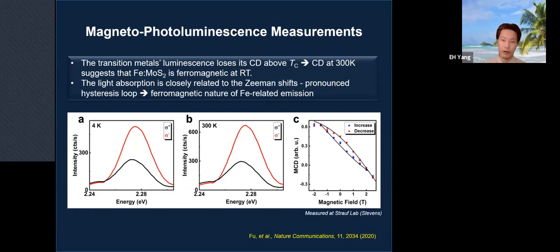And another proof comes from the C, which is a magnetic circular dichroism, where you applied a vertical magnetic field at 4 Kelvin, showing the pronounced hysteresis loop, as you can see, which also confirms the ferromagnetic nature of that iron-related emission. And this is because the light absorption is closely related to the Zeeman shifts, which are associated with the magnetic field. So that shows the existence of magnetism in the material, all right?